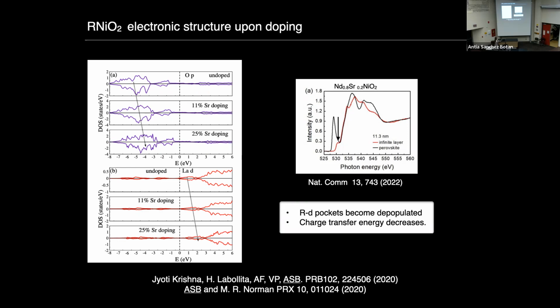So the charge transfer energy again decreases, and that is once again consistent with experiments. These are X-ray absorption experiments at the oxygen K edge for the doped material, where you can see that we have a pre-peak that I mark here by the arrow appearing. This doesn't exist in the parent compound, and that's generally an indication of the presence of oxygen holes. So again, consistent with that, and also with what is found in the cuprates.